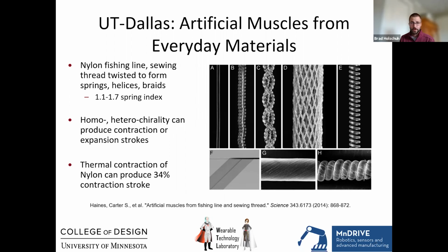There's some really awesome work that's being led out of UT Dallas to try to create, again, fiber-based artificial muscles, and you'll see some pretty familiar structures here, springs, most commonly, twisted fibers into springs, but not made from shape memory materials, not made from alloys, I should say. These aren't nickel titanium, these are nylon. Standard, basically fishing line, a polymer that doesn't have anything particularly special about it, when coiled into these structures and then heated and cooled, can produce pulling forces.